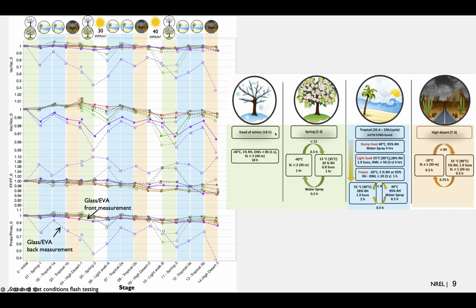So the dead of winter and spring are in green, and the test we take after it is shown as spring. The tropical sequence is split up into two different parts because it's rather long, and that's highlighted in blue. And the high desert is highlighted in orange. We also did some ex situ light soak tests, putting the modules out under sun to see what happens for some additional diagnostics, and that's in white.